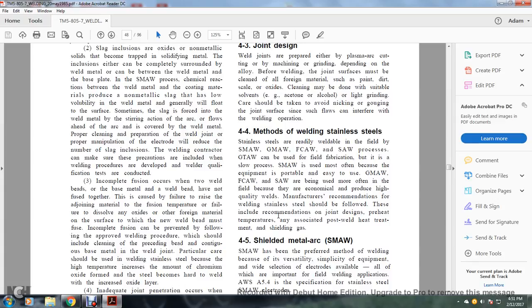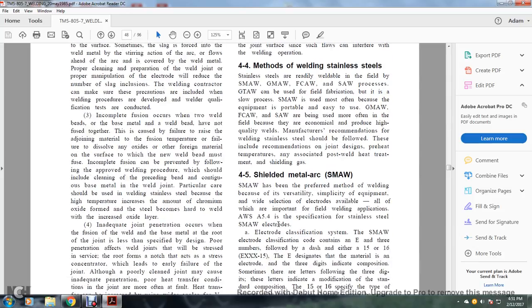4.4 Methods of welding stainless steel. The stainless steels are readily weldable by shielded metal arc welding, gas metal arc welding, flux cored arc welding, and submerged arc welding processes. Gas tungsten arc welding can be used in field fabrication, but it can be a slow process. Shielded metal arc welding is used most often because the equipment is portable and easy to use. Gas metal arc welding, flux cored arc welding, and submerged arc welding are being used more often in the field because of the economical production of higher quality welds. Manufacturer recommendations for welding stainless steel should be followed. These include recommended joint design, preheat temperatures, associated post-weld heat treatments, and shielding gas.